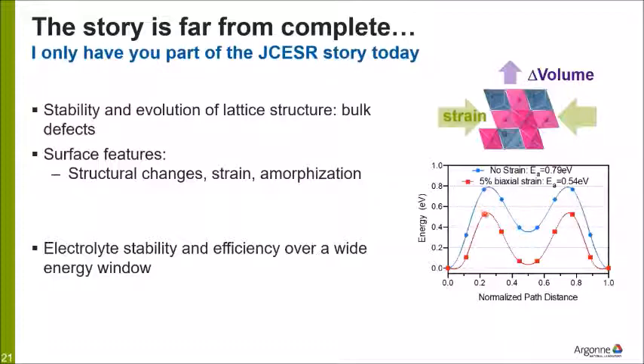And you can see that the biaxial strain actually decreases the energy barrier, so for magnesiation versus magnesium extraction. And finally, like I said, the electrolyte stability and efficiency over a wide energy window is probably one of the biggest challenges that this field faces.